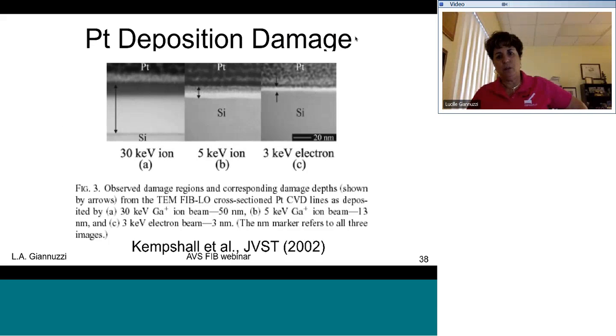You can't even turn on the ion beam if you have a surface-sensitive sample. Deposit the region of interest with electron beam deposition first, and then you can use ion beam deposition on top. The reason why people use both is because electron beam deposition is so slow. So you can get about 100 nanometers of electron beam deposition on top of your sample, put ion beam deposition on top of that, and that will prevent ion beam deposition damage to your top layers.